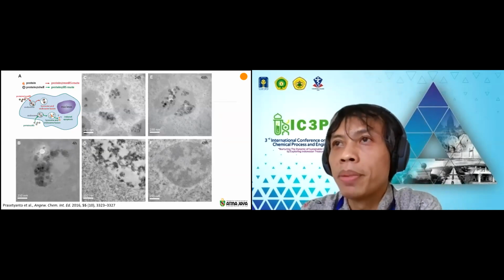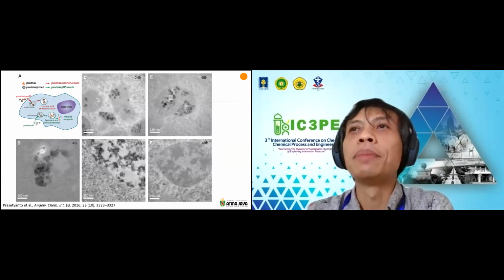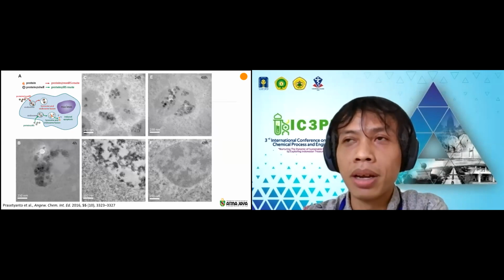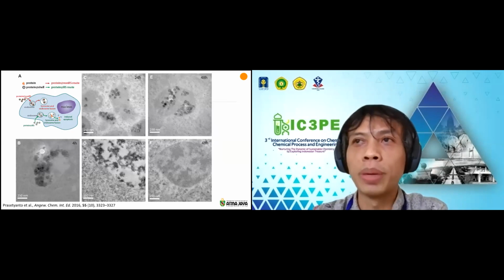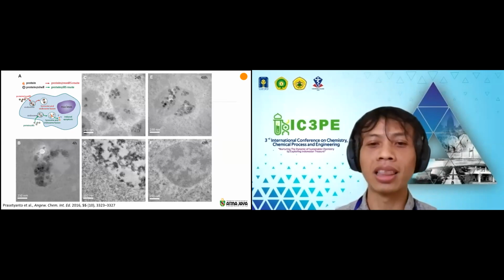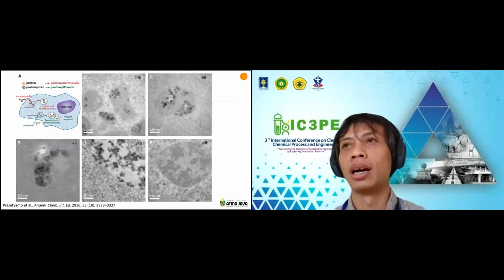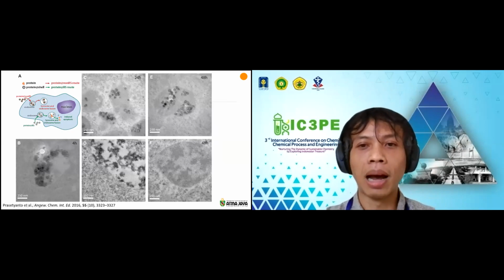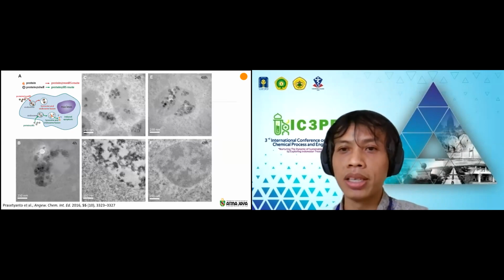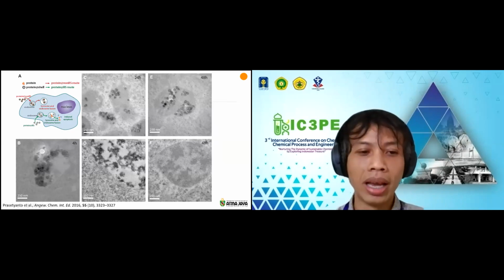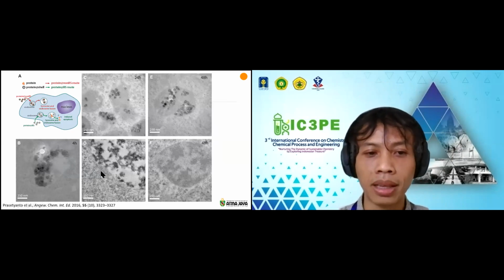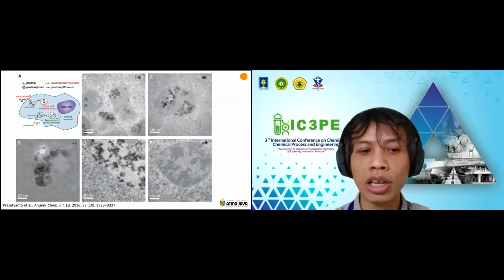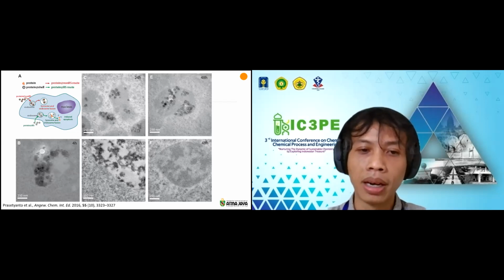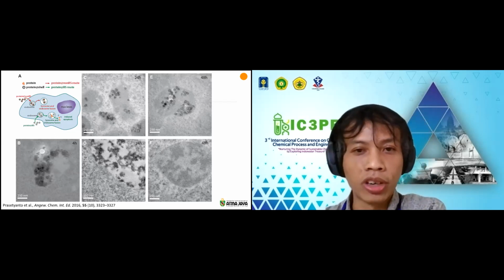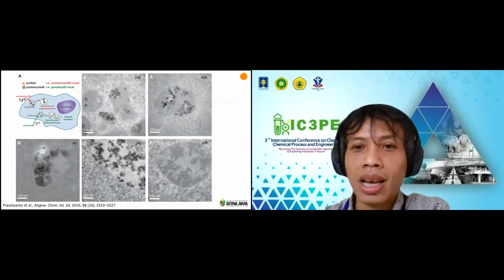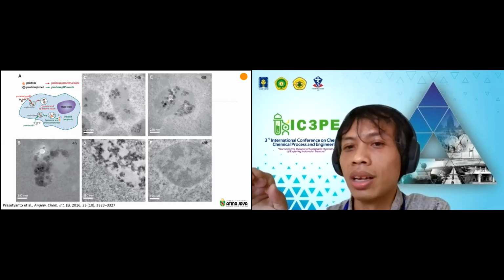So to prove that our breakable nanoparticle can really break inside of the cell, we did some experiment by incubating the cell with our particle, and then we sliced it and put it under the TEM. The upper side of the picture of the TEM images is the non-breakable material, while the bottom part is the cells which we incubated with our breakable nanoparticle. After 48 hours, we can see clearly in the upper side that the nanoparticle is still there.